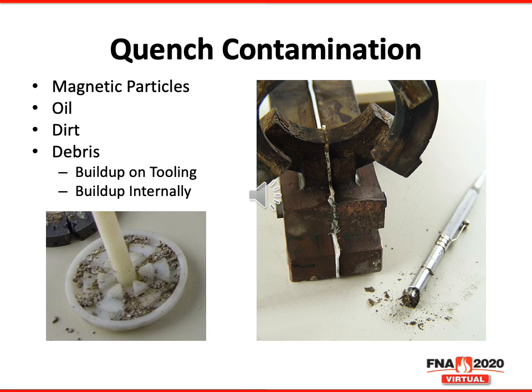When filters are not used or maintained, we see repairs much more frequently. We often see contaminants such as oil and dirt in the quench chambers. We see inductor coils come in for rebuild with a heavy patina of dirty, crusty contaminants. These contaminants are commonly a buildup of magnetic particles attracted by the magnetic field generated by the inductor coil. This patina accumulates and creates a short circuit, usually damaging the inductor coil.